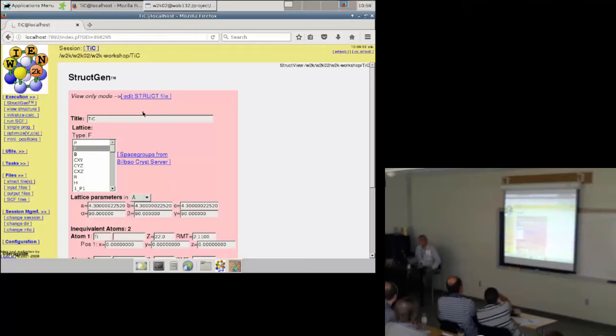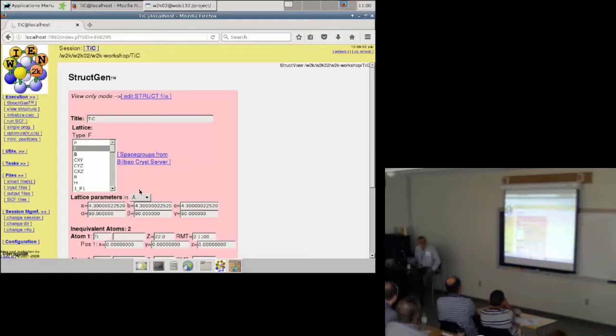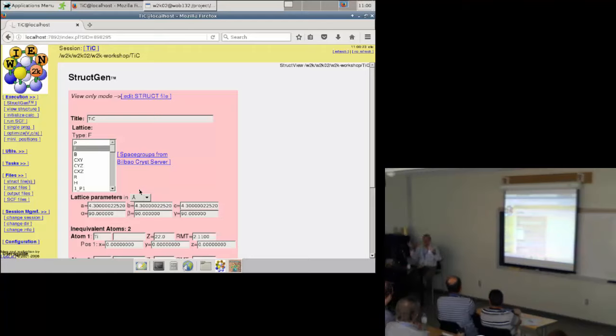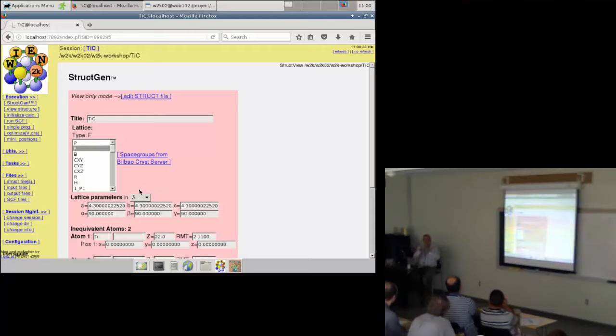The new sphere sizing scheme gives a better scaling between titanium and carbon, so you should use the new scheme. If you know the space group, put it in. If you don't know the structure and only know it has two atoms, you would test sodium chloride, cesium chloride, zinc blende, and other structures, and hopefully find the best structure by total energy comparison.